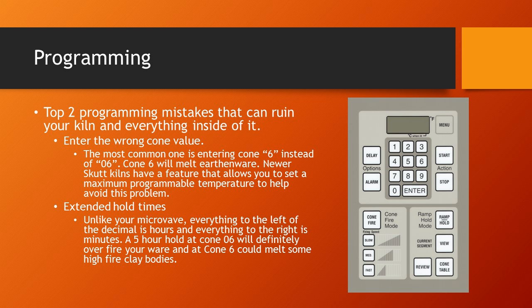Okay, so programming. The 2 most common ways of ruining your kiln is, 1, putting in the wrong cone value. So many times, if you don't train your employees correctly, they hear, oh, I need 6. And you're firing to 06. If you have earthenware clay in there, it is all going to melt to the bottom of your kiln and probably ruin your kiln. We have a new feature that I'll talk about in a little bit that would prevent them from doing that if all you're doing is low firings.